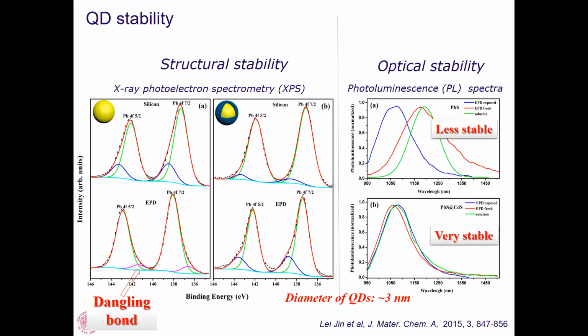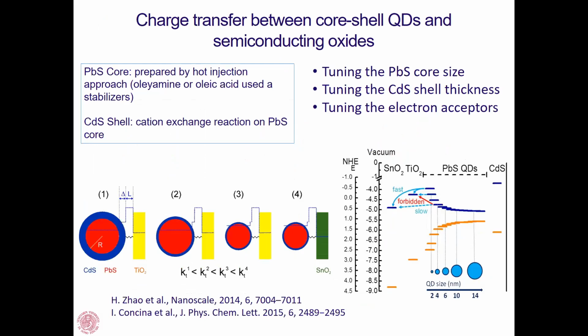To avoid the surface oxidation, we tried to cover our crystals with an insulating shell. It's a cadmium sulfide shell, and we succeeded in demonstrating that the core shell is much more stable than the simple crystal. We also investigated how the core shell structure influences the charge dynamics when you have your quantum dots integrated in a few different matrices. We first tried titanium oxide and tin oxide, demonstrating that by changing the size of the core and the thickness of the shell, you can tune the ability of electrons to be transferred from the photoexcited crystal to the oxide. And of course, this kills the photoluminescence of your system.